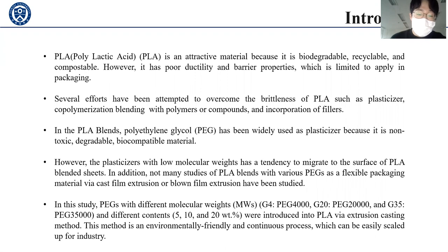In this study, PEGs with different molecular weights, 4,000, 20,000, and 35,000, and different contents, 5, 10, and 20%, were introduced into PLA via the extrusion casting method. This method is an environmentally friendly and continuous process, which can be easily scaled up for industry.